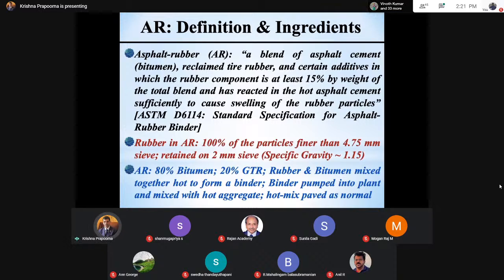For example, if you're blending a gap graded asphalt rubber, the binder content can vary anywhere between 6 and 8%. You people are familiar. If you go to the Indian Roads Congress specification, for the dense graded, the binder content shall be anywhere between 4.5 and 5.5%. Right here, you see it is a rich binder. Why are we making it so rich? Because there are rubber inclusions.